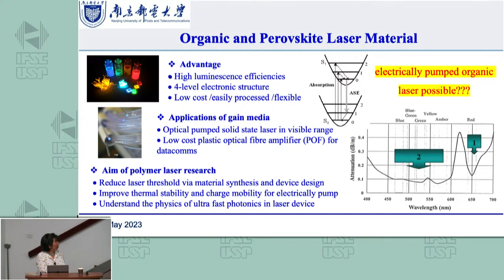For our work, in one direction, we identify organic laser materials and try to fabricate a plastic fiber amplifier, using plastic like PMMA. In the attenuation spectrum, there is a very low loss window at 650 nm, and for the whole visible part, PMMA gives very low losses. So it's worth trying to make a plastic fiber amplifier.